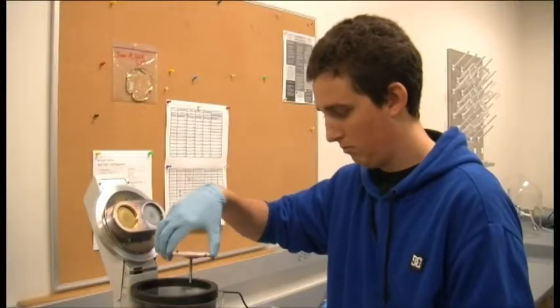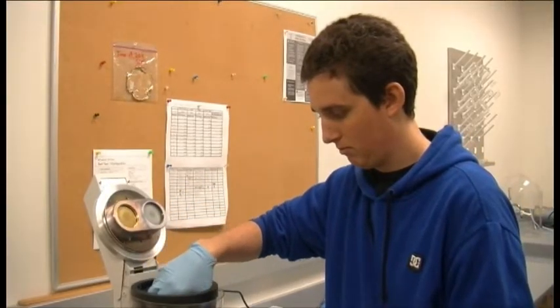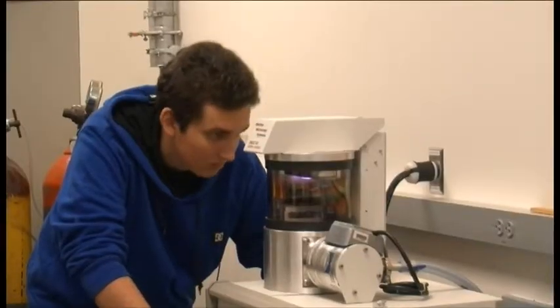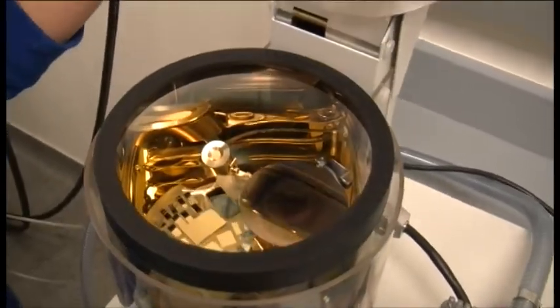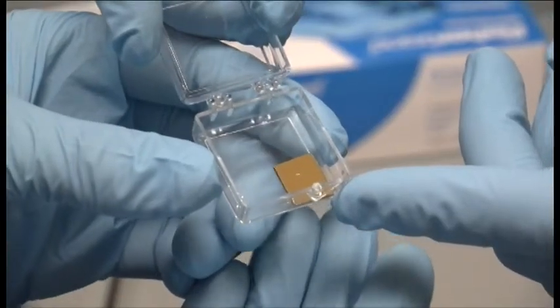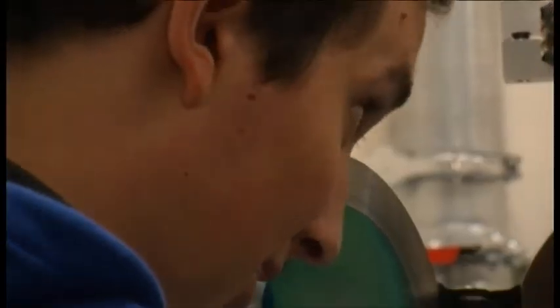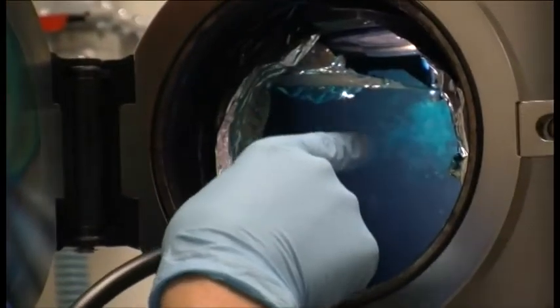The first thing we had to do was learn how to prepare thin films of phthalocyanine. The students in my lab have investigated the conditions required to prepare films with the surface features we wanted. Here is Matt, one of the undergraduate students in my group, preparing a set of thin films for testing. We start with a substrate wafer and coat it with a very, very thin layer of gold. Then we place the wafer in an organic thermal evaporator and we add a crucible of phthalocyanine.